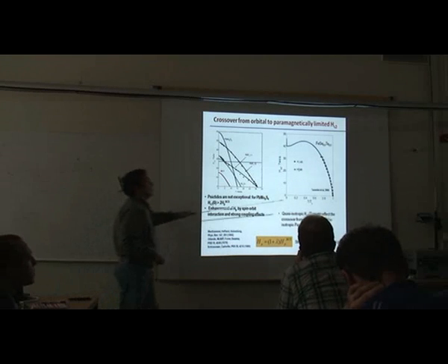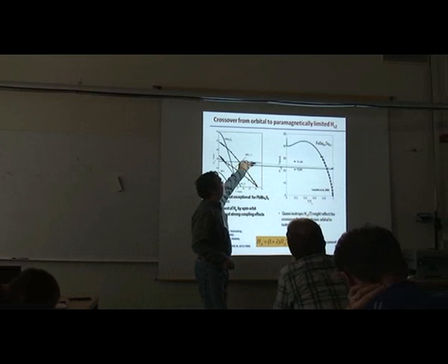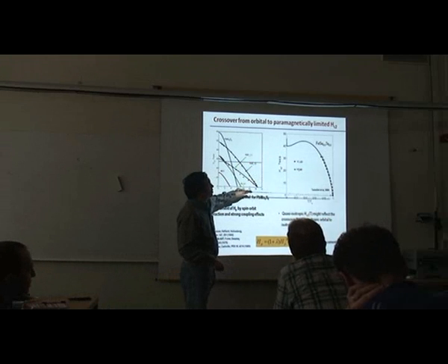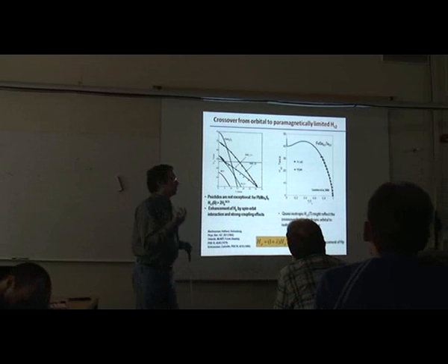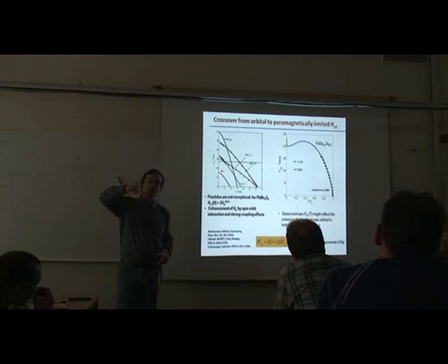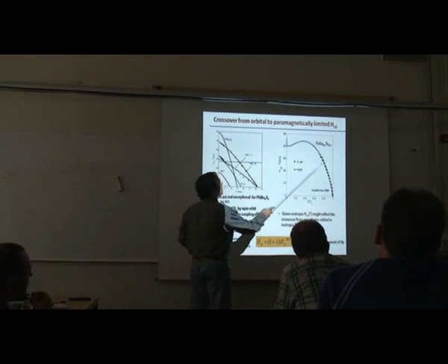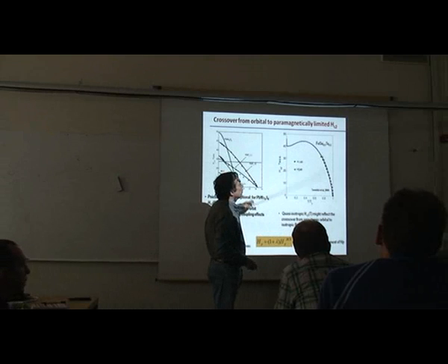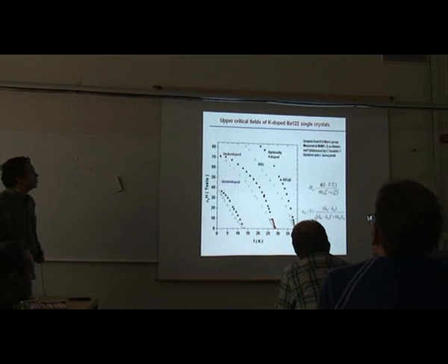Now, when we did measurements for this material, again we're limited by the 30 Tesla we have in Tallahassee. You can see that HC2 starts almost vertically here. And what I did for fun, I took the curve for the Zeeman paramagnetic field calculated in 1963 by Sarma, which simply neglects orbital pair breaking and takes into account only Zeeman terms. This curve looks like this. It fits perfectly from here to here. Unfortunately, we didn't have enough data points to say more.